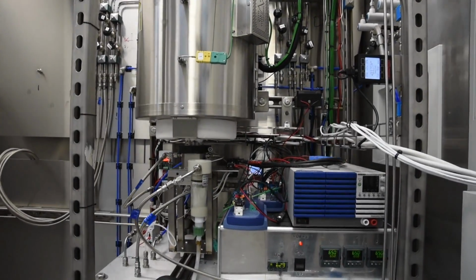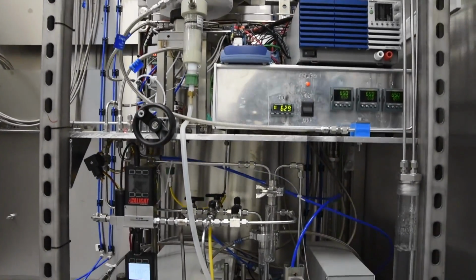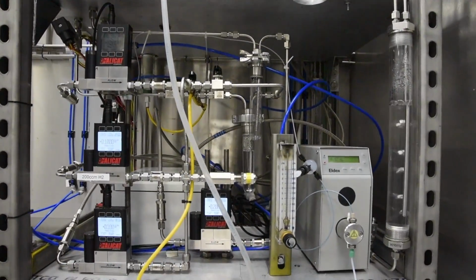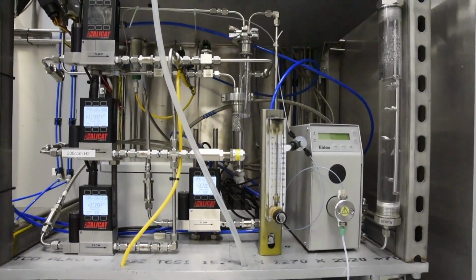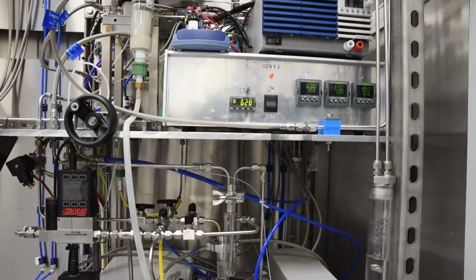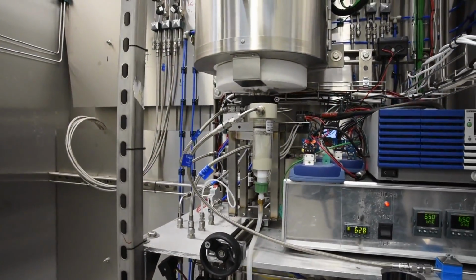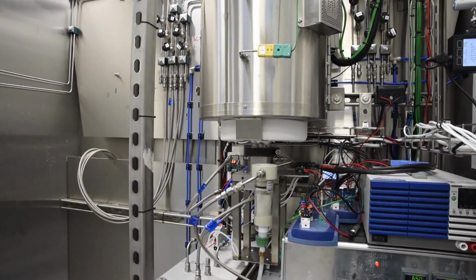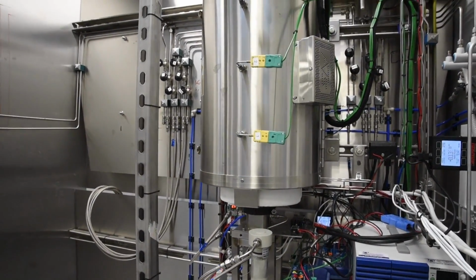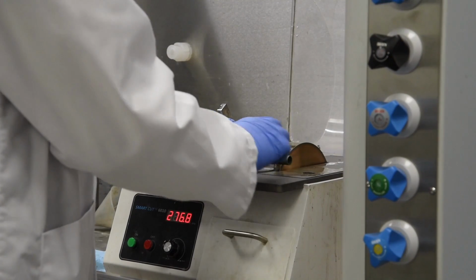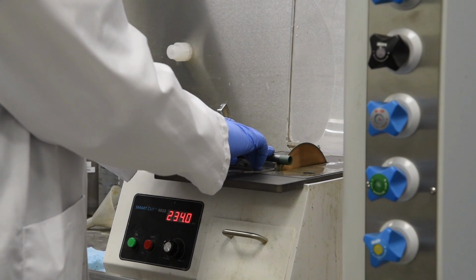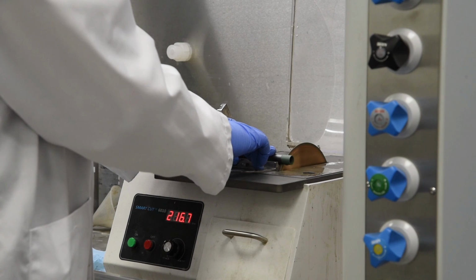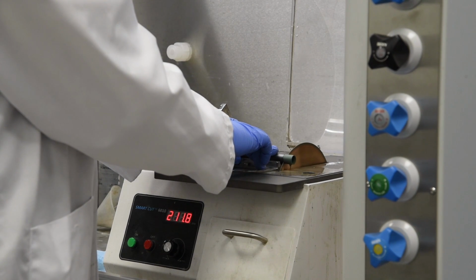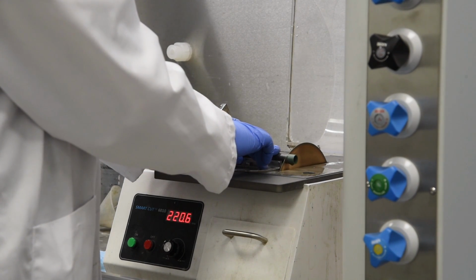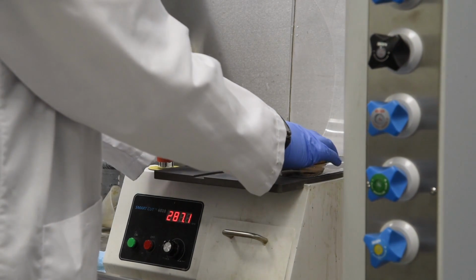Our state-of-the-art single-cell test stands can emulate real-life reactor and stack conditions. These test stands allow us to change multiple parameters and optimize our operating conditions to increase cell durability and performance. Our stands can also simulate life tests on the materials that we use. We can then take the data off the single-cell test stand and use those same operating conditions and parameters on our stack tests. Once the cells complete their tests, we perform post-mortem analysis in our state-of-the-art analytical and optical lab.